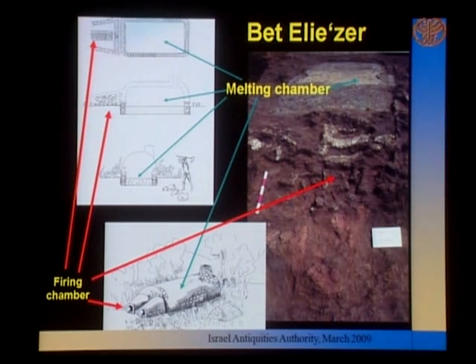If you do the math of 17 furnaces, each one produced about 10 tons of glass, you reach a considerable mass. This large-scale production was intended for the making not only of vessels, but also mosaic floors, window panes, and lighting devices for the local market as well as for export. The raw glass from this region was traded all over the Mediterranean and probably found its way to glass workshops in the Byzantine Empire, possibly even to the capital, Constantinople, and to the emperor's court.